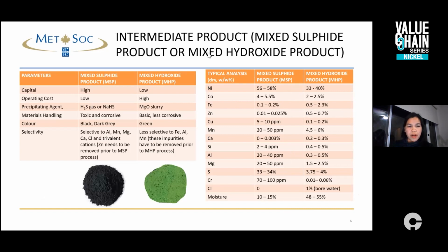So in terms of direct comparison, mixed sulfide processing typically requires higher capital. It's because the process in itself is very corrosive and toxic. So it needs a scrubbing process and also H2S destruction, and the materials of construction for the area are mostly exotic, whereas mixed hydroxide is typically less aggressive, and the materials of construction can just be carbon steel and rubber lining.